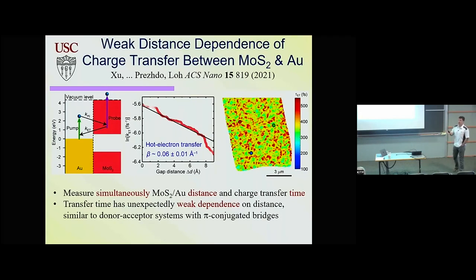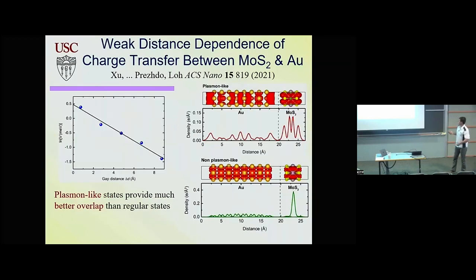If you had vacuum between gold and MoS2, it would decay very fast. But this fast decay shows up only at a distance of 8 angstroms or so, almost 1 nanometer. And below that, decay is very slow. And this is exactly, in our explanation, for this reason: you have plasmon-like states that extend pretty far into the vacuum. And those states facilitate charge transport that is much more efficient than you would expect if you just assume you have vacuum there.